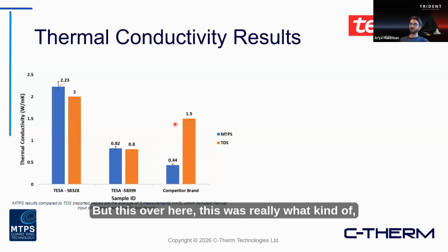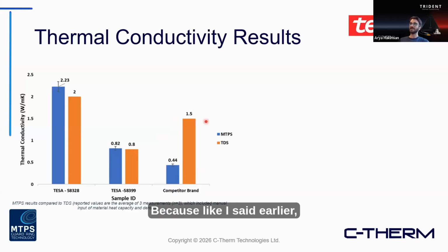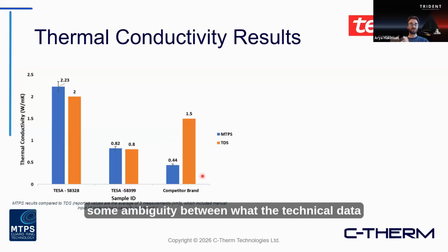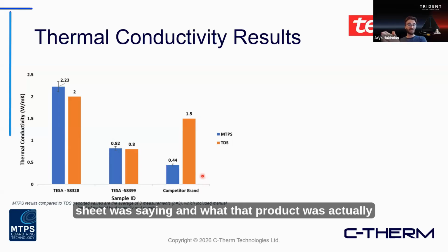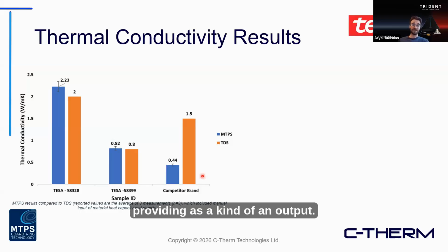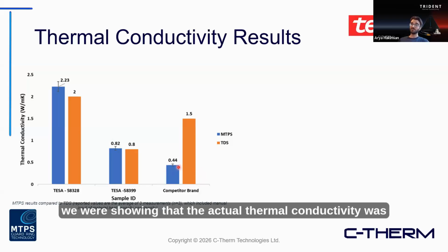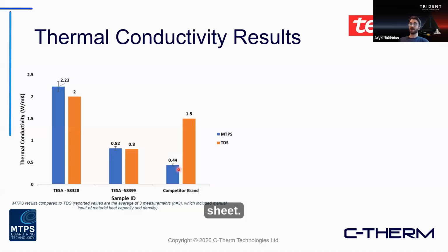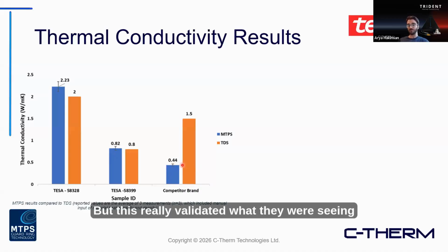But this over here was really what helped answer some questions for them, because like I said earlier, in situ, they were seeing some ambiguity between what the technical data sheet was saying and what that product was actually providing as an output. And when we did the test, we showed that the actual thermal conductivity was significantly lower than what was on that spec sheet. But this really validated what they were seeing with some of the issues there.